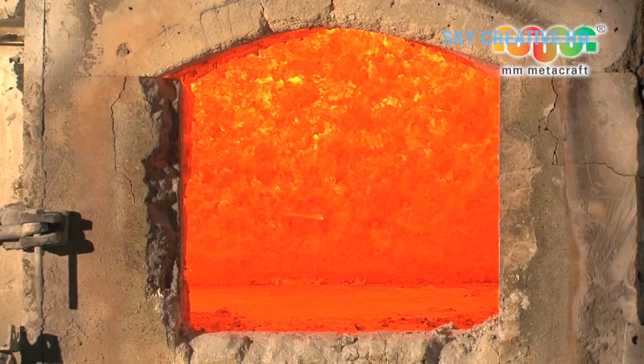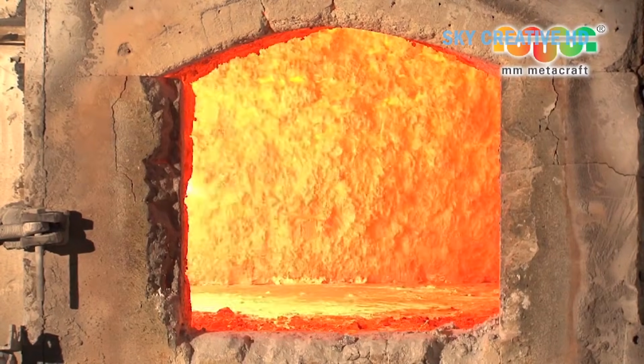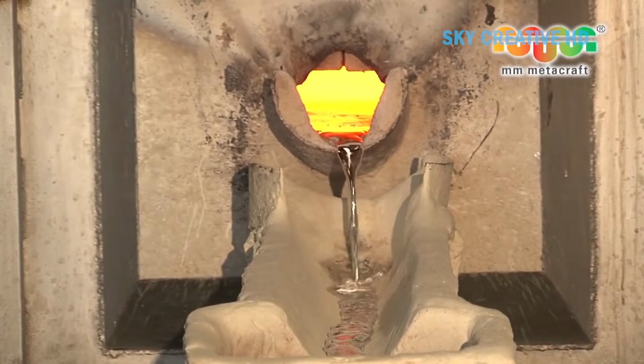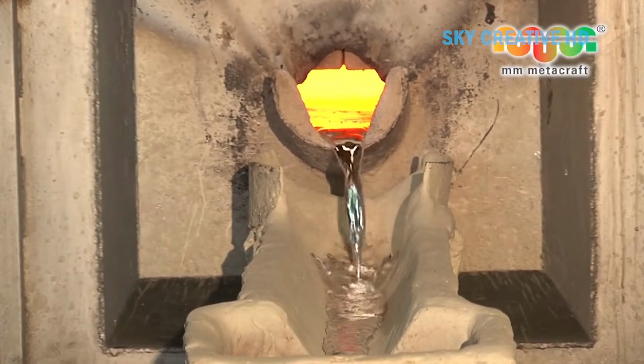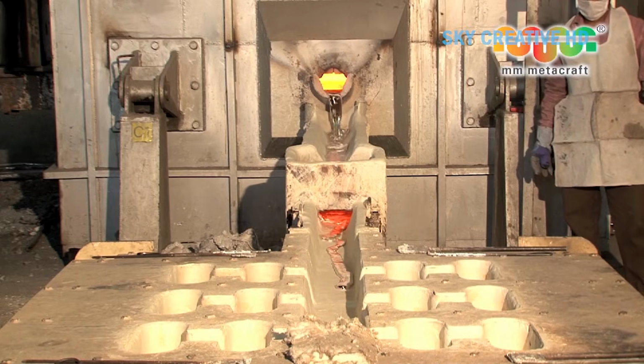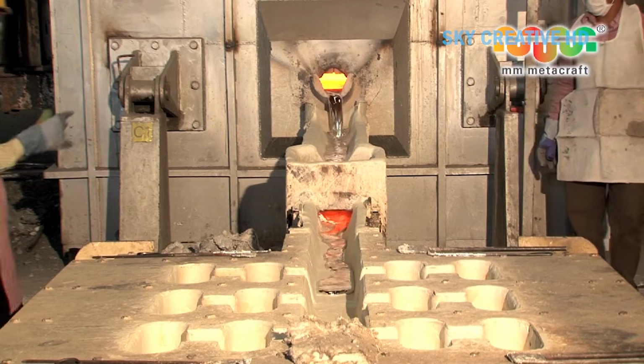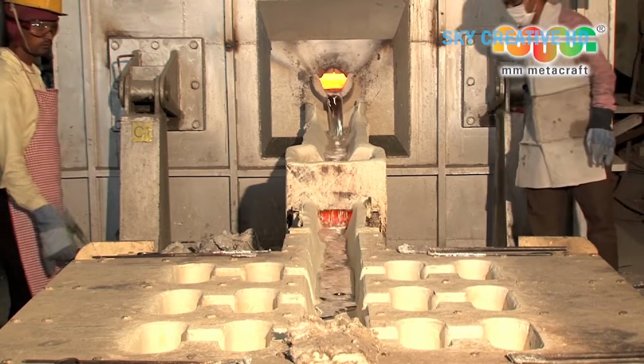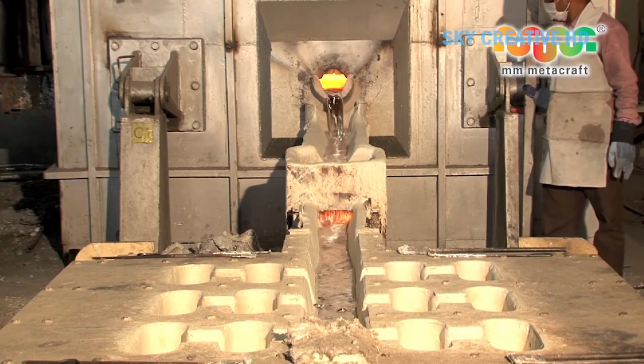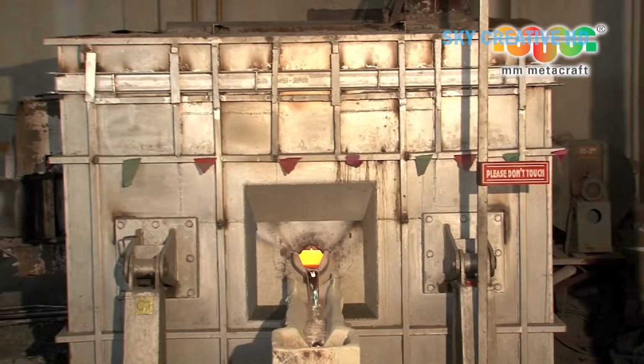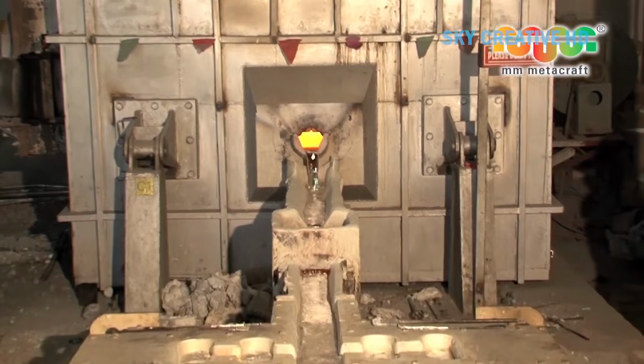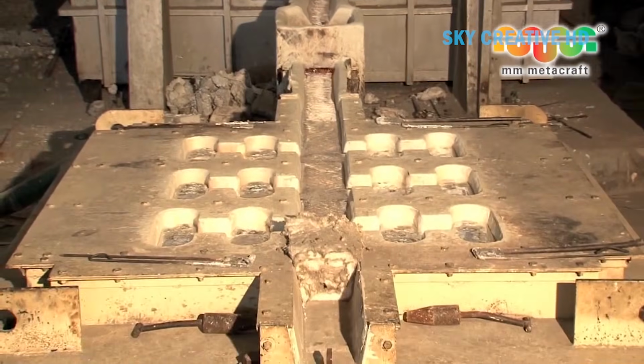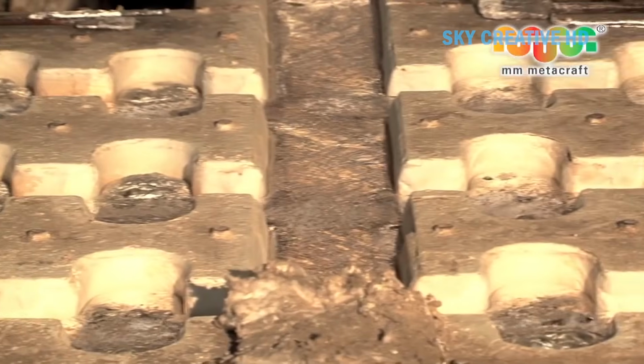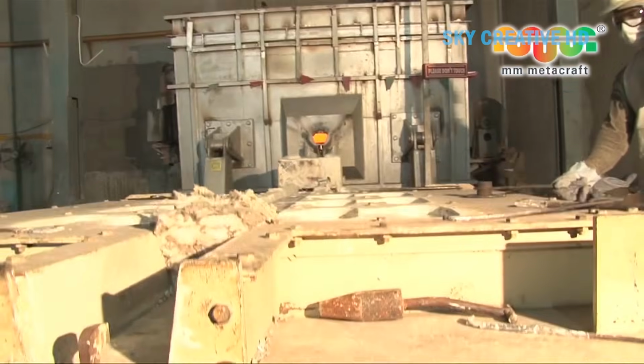Before the billet goes anywhere near the press, it has to be heated. And this is where MM Metacraft's internal hot melting furnace setup becomes relevant. Rather than sourcing pre-cast billets from an outside supplier, a vertically integrated operation melts its own aluminum and casts its own billets on site. The billets are heated in a log furnace to the extrusion temperature, typically between 750 degrees Fahrenheit and 950 degrees, 400 to 510 degrees Celsius for 6xxx series alloys. The exact temperature profile matters.